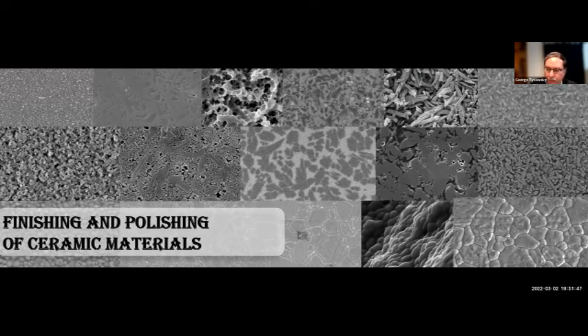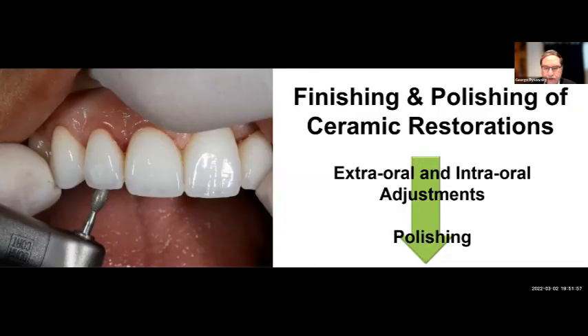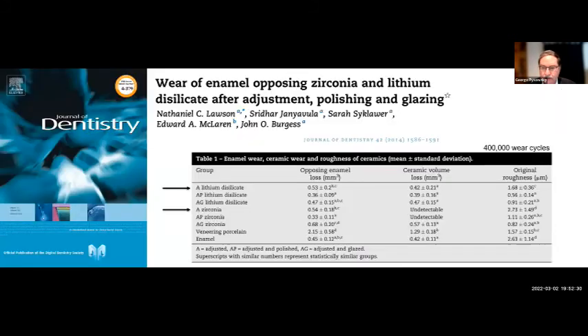Polishing and finishing is actually more important than glazing in many situations because it provides the ideal surface, especially after the glaze wears off for these restorations. So it's very important to look at either extraoral or intraoral adjustments. If we adjust a restoration, either extraorally or intraorally, it's very important to go back and provide a very fine finish to that material so it has a glassy, smooth interface for the viability of functional areas and especially in contact areas overall. So we want to use very fine diamonds, high copious water spray, and then finish them off with a sequence of high fine polishers to provide that glassy surface accordingly.